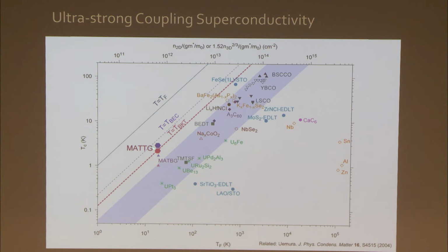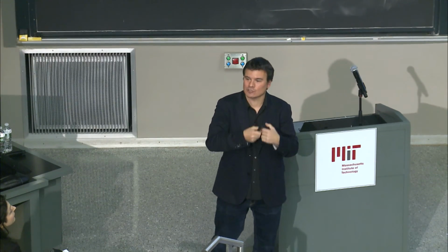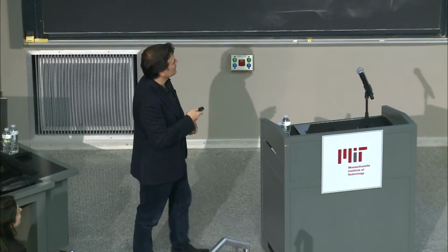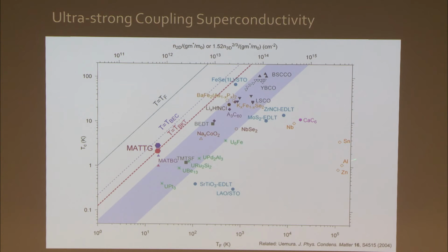Magic angle twisted bilayer, in particular tri-layer graphene, are here. The pairing glue that connects electrons and makes them superconduct is the strongest by far for any material, okay? They have similar critical temperatures or higher actually than aluminum with 4 or 5 orders of magnitude less density of electrons, okay? So that's something we do not understand exactly, how come that with such a tiny density of electrons, magic angle graphene superconducts so well, okay? And part of the community is trying to see if we can understand that properly so that if we are able to extract the basic physics, the basic ingredients that are responsible for this, perhaps we will be able to engineer those basic principles at regular metallic densities so that critical temperature will be well above room temperature. Okay, that's part of the motivation for a fraction of the community.